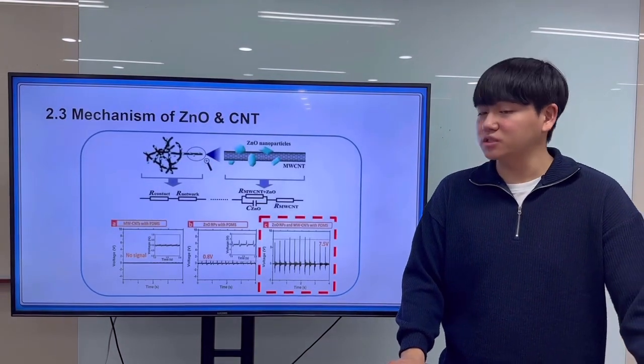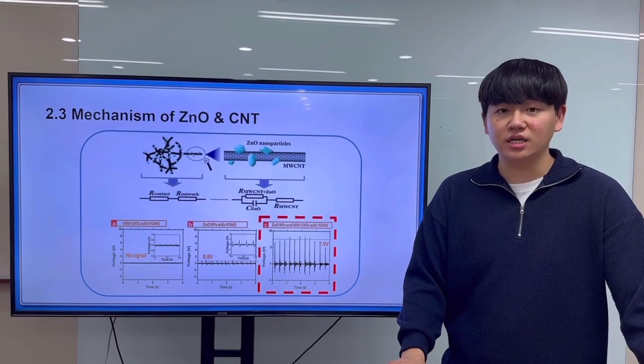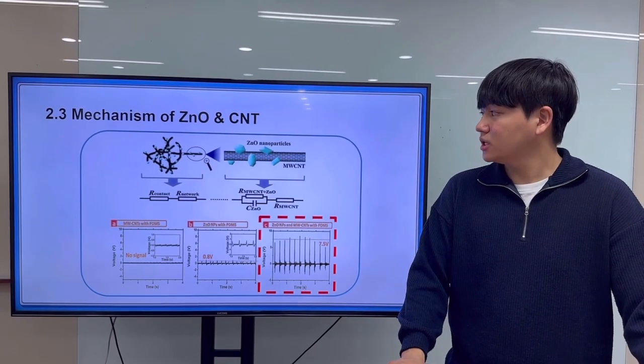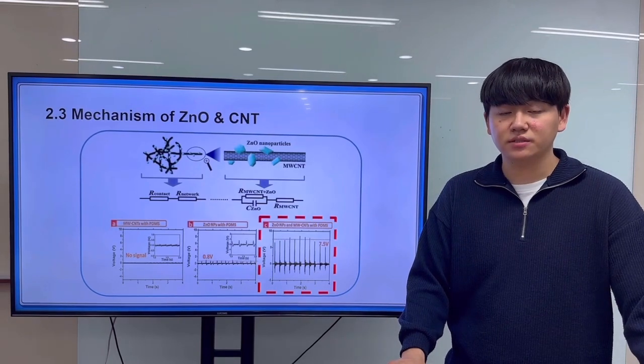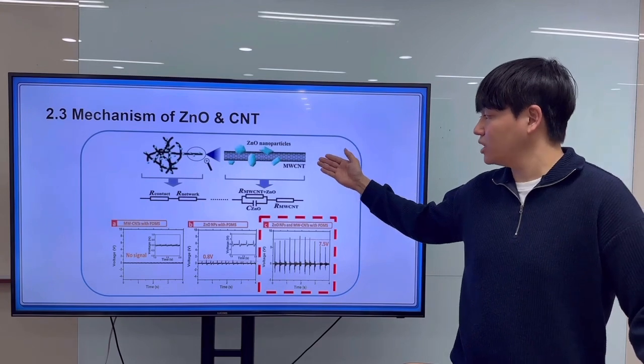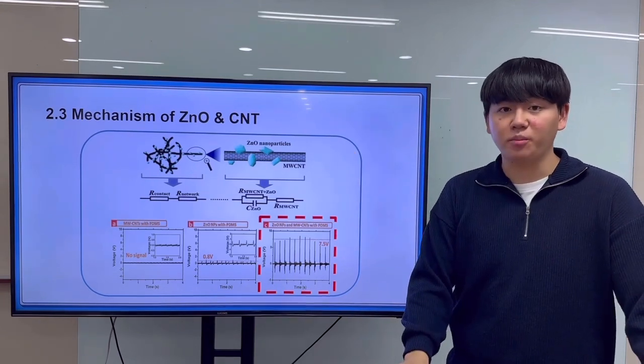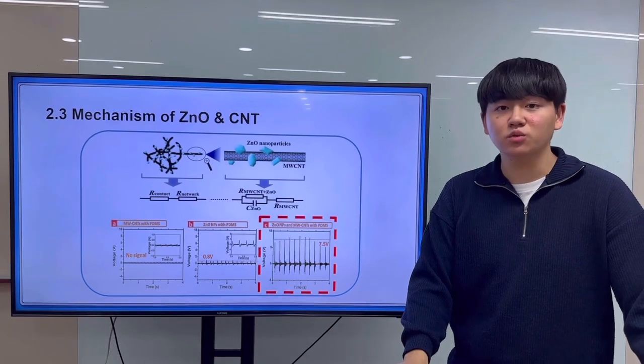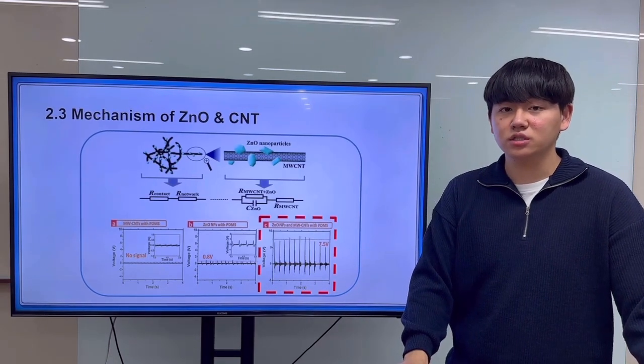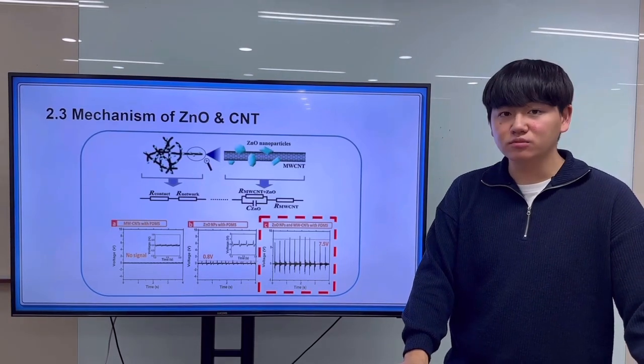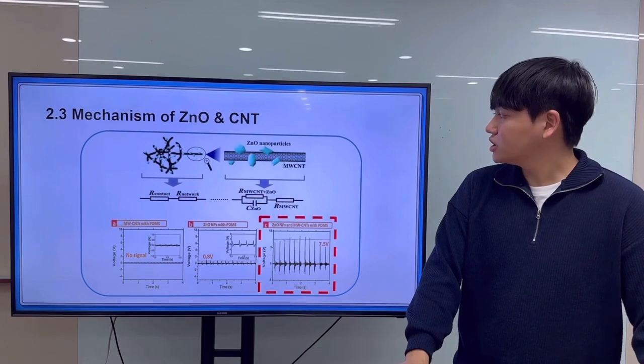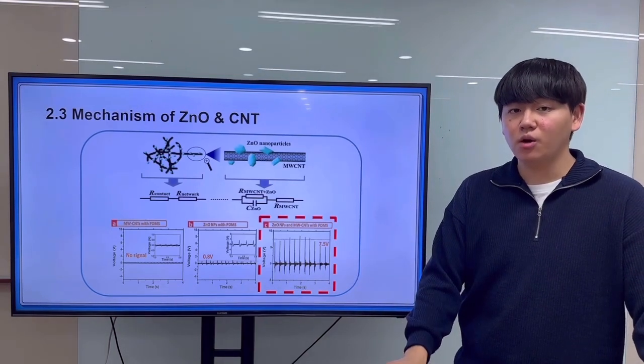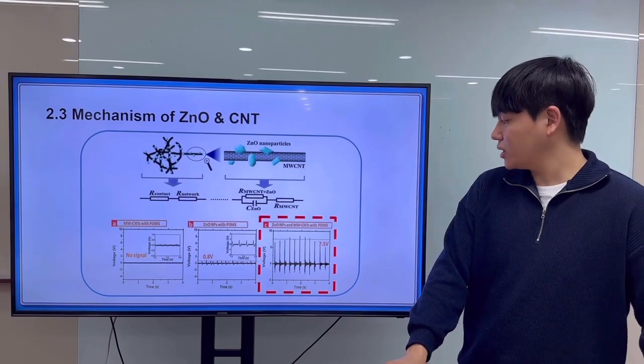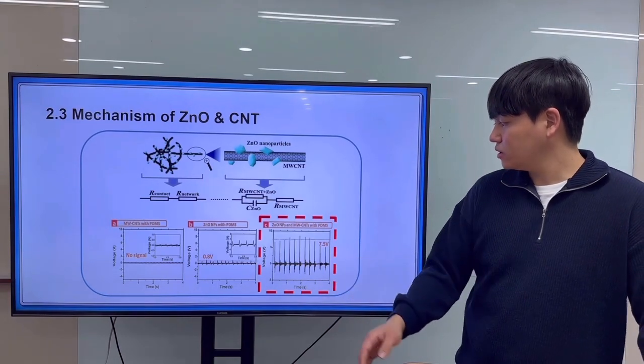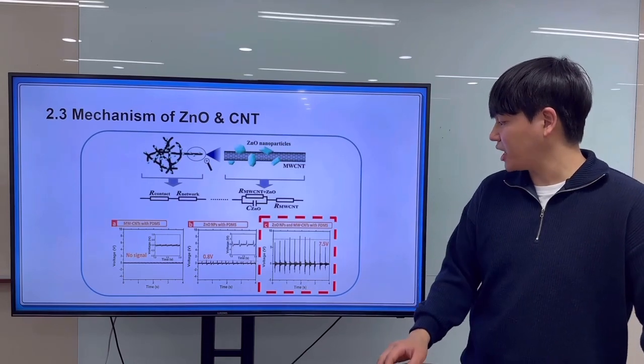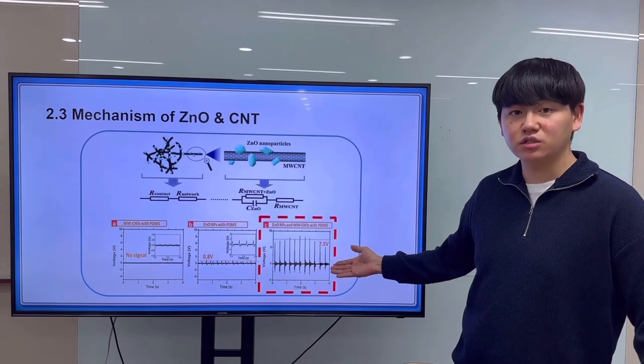Now there is a mechanism of zinc oxide and CNT. We mix zinc oxide with CNT. It is one of the key points of our device. CNT can make a nanoelectrical bridge among zinc oxide nanoparticles. This is the reason why we use CNT. In other words, CNT can make it easy to move energy to upper and lower electrodes while hopping. You can also see in the graph below, the voltage is best when we add CNT into zinc oxide.